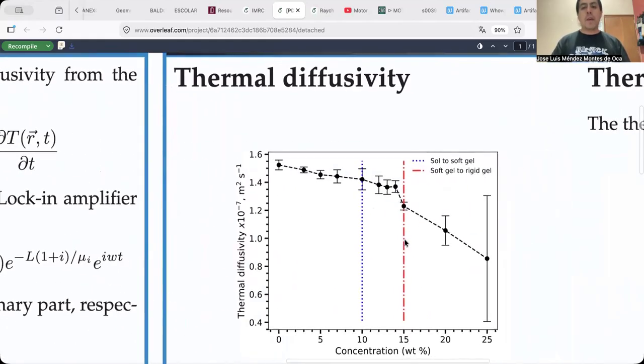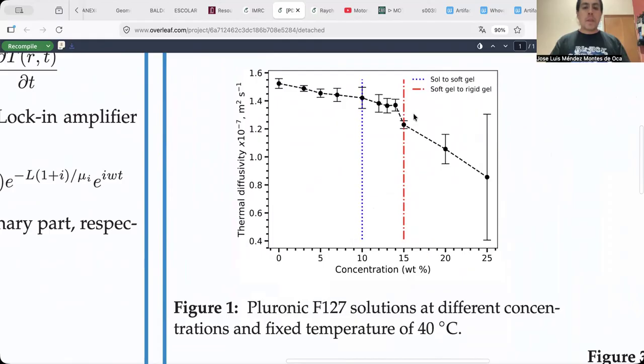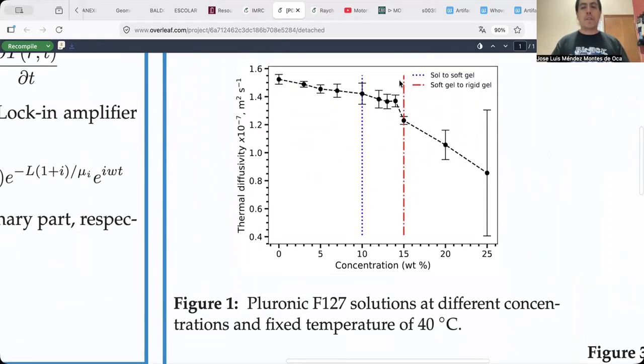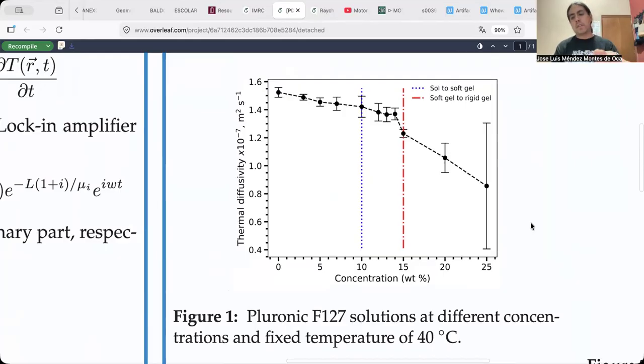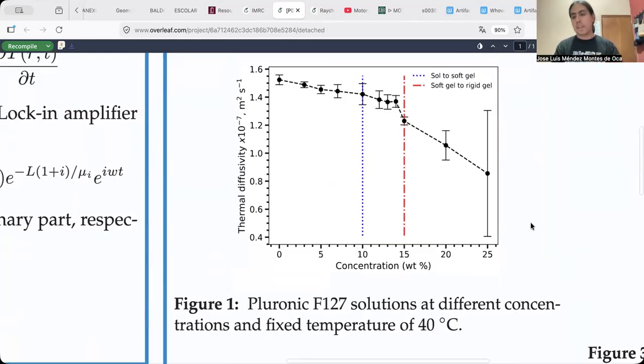And using this technique, the thermal diffusivity of some samples with different concentration was obtained at a fixed temperature of 40 degrees Celsius. Here, the transition from solution to soft gel is depicted as the dotted blue line, and the transition from soft gel to rigid gel is depicted as the red dashed line, and changes in the slope of the thermal diffusivity curve are observed in these transitions. Then, even from these early results, it can be observed that the transition can be detected with this method.